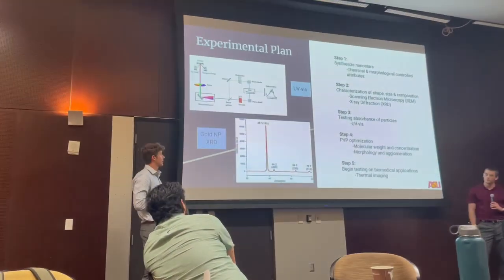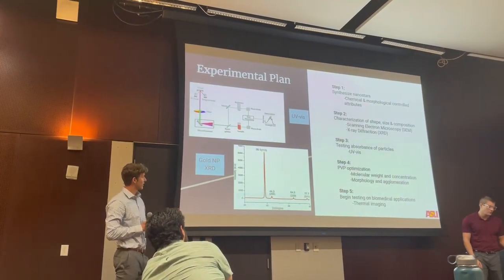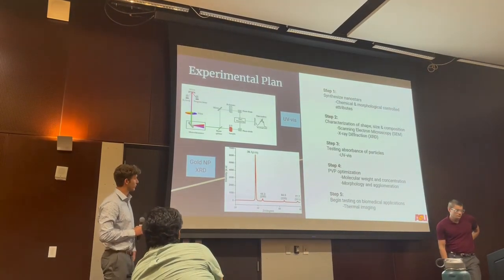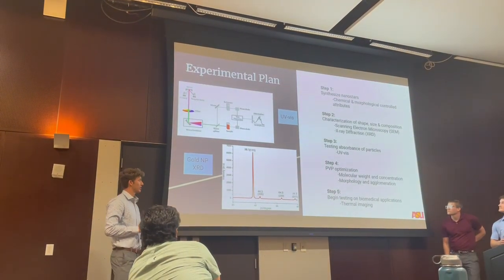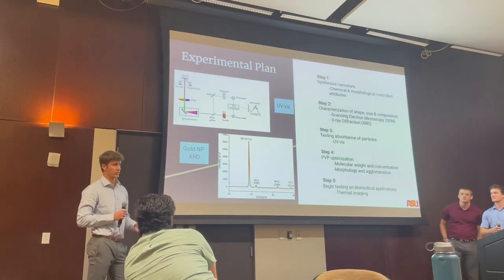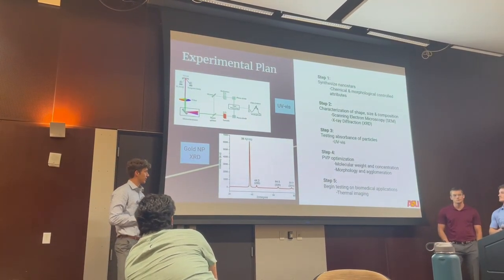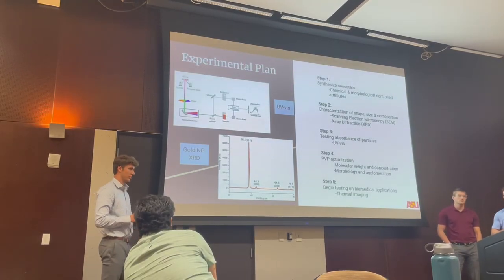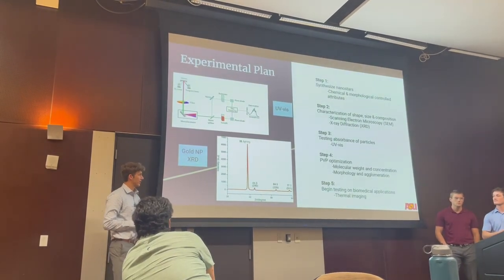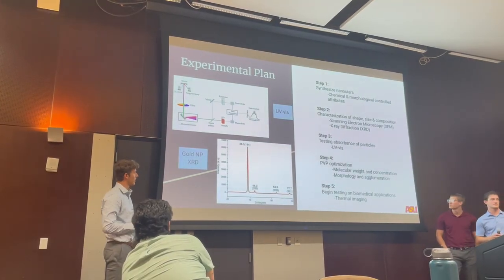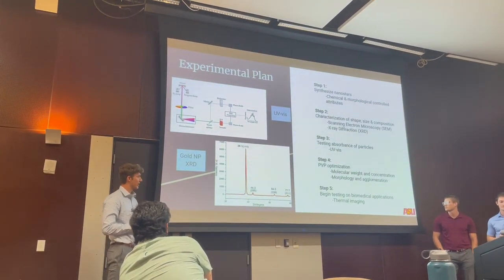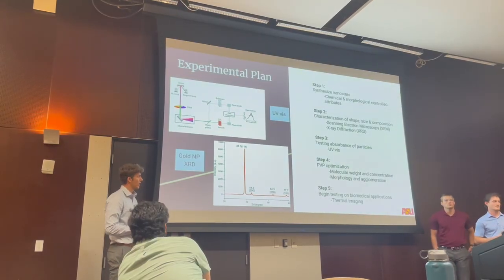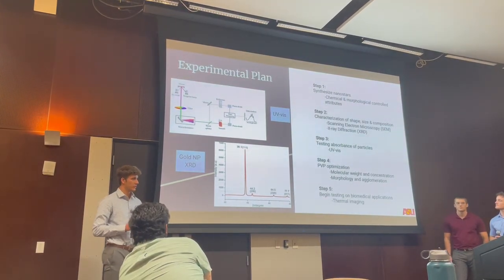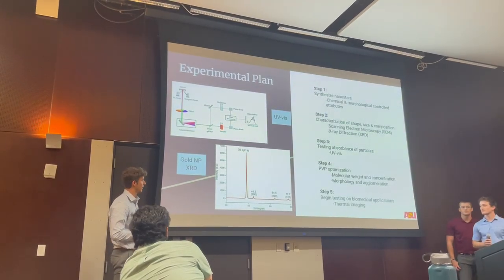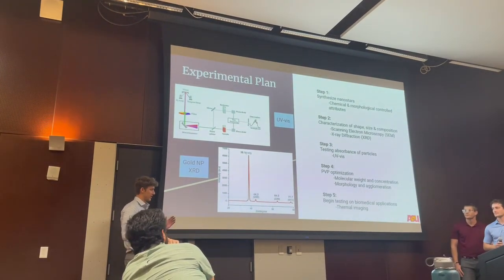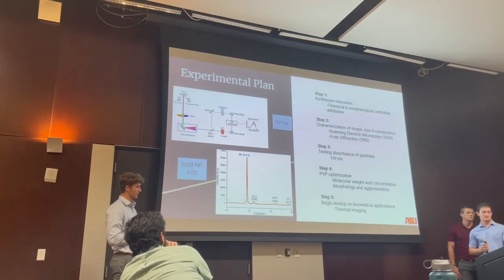All right, so going into our experimental plan a little bit, we'll start off our project by synthesizing these nanostars. Once we've done that, we'll start characterizing their shape, size, and composition by using scanning electron microscopy, SEM, as well as X-ray diffraction, XRD. Once we've identified that we have particles and they're roughly the morphology we want, then we'll go into testing their absorption using UV-Vis. And then once we've gone through those 3 steps, we'll reiterate them, adjusting the PVP molecular weight and concentration to get optimal morphology, agglomeration, and absorption characteristics. And then once that's all done, we'll begin testing thermal imaging to see it actually heating up inside of a substrate.